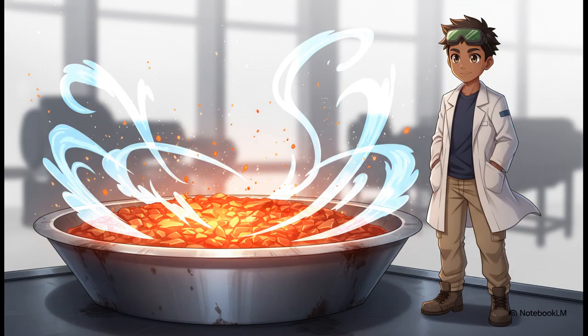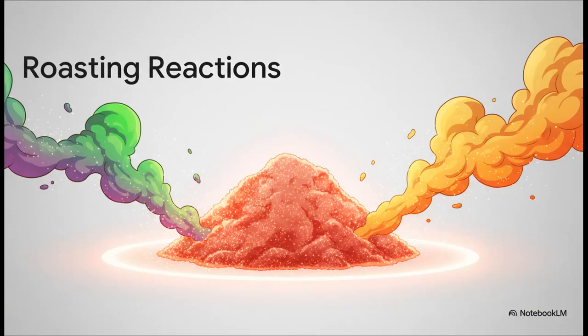contaminate the final product. As that intensely hot air hits the powder, nasty impurities like arsenic and antimony react with the surrounding oxygen. They oxidize, forming arsenic trioxide and antimony trioxide, effectively burning away into the exhaust. At the same time, our primary ore, which is mostly copper sulfide, reacts with the oxygen to form copper oxide. But here's the catch. This conversion releases a very heavy, highly noticeable byproduct, sulfur dioxide gas.